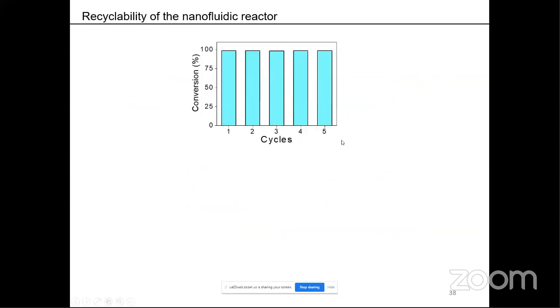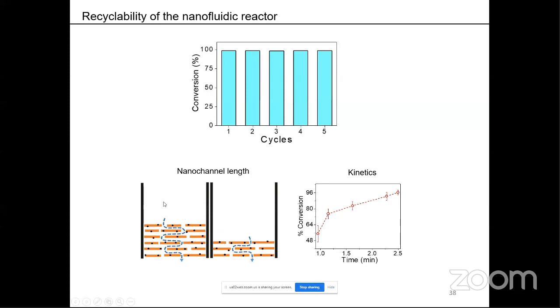Similarly, we have carried out the reactions through the membrane multiple times, and we see that in almost every case we get around 100% conversion for the nanofluidic channels. Similarly, we can also change the nanofluidic channels through which our reagent goes in a zigzag way through the catalyst. If we make a very thick film, it takes a long time for the molecules to go through the channels. If we make a small channel, it goes so quickly, and based on this time, we can measure how the conversion changes as a function of time.